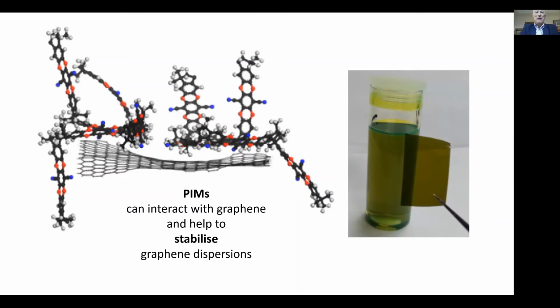Now, I've talked a little bit about the polymers that we refer to as polymers of intrinsic microporosity, or PIMs, and I've talked a little bit about graphene. But actually, the two are in a sense quite similar. The rings in a PIM are quite like the rings in graphene. They actually interact with each other quite effectively. And indeed, PIMs can stabilize graphene dispersions, and we can make films which are a mixture of PIMs with a little bit of graphene. And we'll see later how those might be useful.